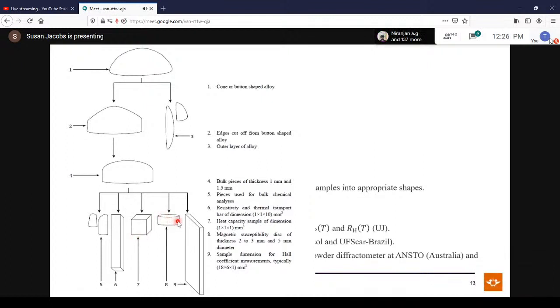For magnetization and magnetic susceptibility measurements, the samples are loaded in a straw, so you would have a circular cross-section. Moreover, you want a uniform distribution of moments about the central axis. Therefore, the ideal shape would be a disc of about 2 to 3 millimeter thickness and 5 millimeter diameter.